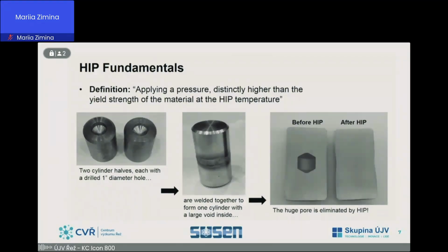There is an example showing what HIPping can do. In the left picture here, we have two steel rods that have drilled holes in the ends. We put these ends together and weld them, and we created a slightly bigger cylinder with a big void inside. These specimens were HIPped, and we can see the results in the right picture. There are cross sections. The left specimen is the reference that has not been HIPped. We can see the big void there, or the big vacancy. The specimen to the right was an identical specimen, but it was HIPped and then cut up, and we can see the big void was eliminated.